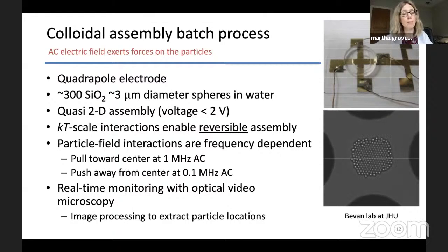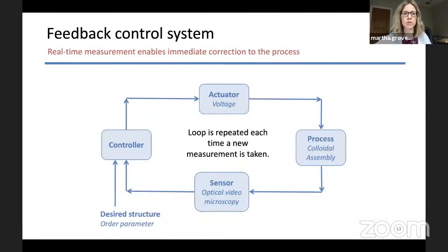We have reversible assembly by setting our salt concentration to enable reversibility. And we can either push or pull the particles toward the middle, depending on the frequency of the applied voltage. But we have really only one knob on the system that we're going to use today, which is the amplitude of the voltage. And we're going to stick with a fixed attractive frequency. But we have full state feedback by real-time monitoring with optical video microscopy and image processing to extract all the particle locations in real time. And we can actually do this much faster than the dynamics of the system. And so sampling rate is really not a limitation here.